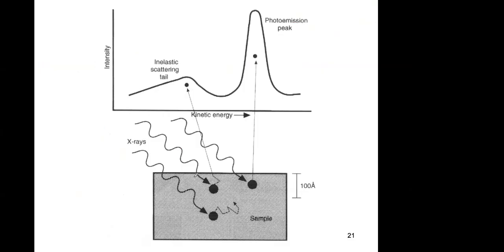So that's basically what it says here. These are the main peak. This one didn't lose energy, but if you lose energy, you have an inelastic scattering tail and you will have an increase in the background because they are coming from deeper. X-rays can penetrate 1,000 angstroms or more, and you will have Auger electrons up here, XPS electrons down here, but they are not able to come out because they're too deep.